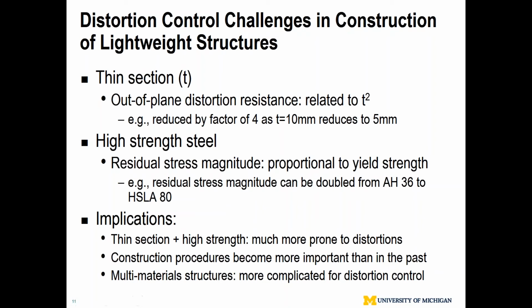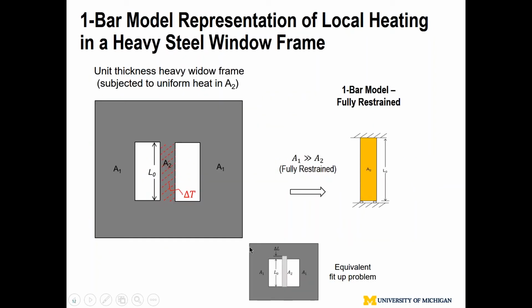Regarding the buckling distortion we have seen from the friction stir welding example and the shipboard buckling example, the distortion resistance, essentially in terms of stress, is proportional to T squared. That's why in the shipbuilding industry, and also in armored vehicles, when you talk about lightweight, let's use a simple number. If originally you used 10 millimeter thickness and now that is reduced to 5 millimeter, you are talking about a factor of 4 reduction in buckling distortion resistance. That's why the shipyard in the past, dealing with 10 millimeter, didn't see much buckling distortion. All of a sudden, starting about 15 years ago, you see all kinds of distortion issues.